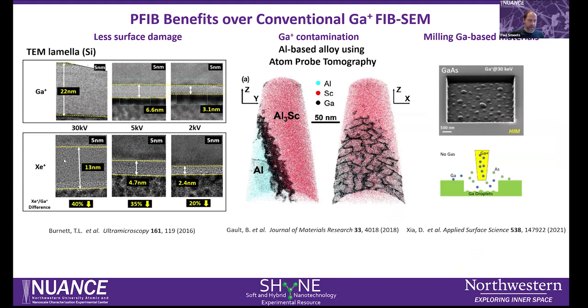For example, this is a paper where they prepare a TEM cross section. With a micromanipulator, you can lift out a small volume, thin it down to electron transparency, transfer it over to the TEM, and then measure the surface damage on a silicon sample.